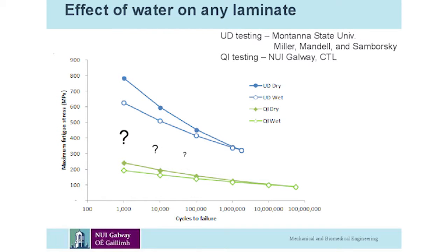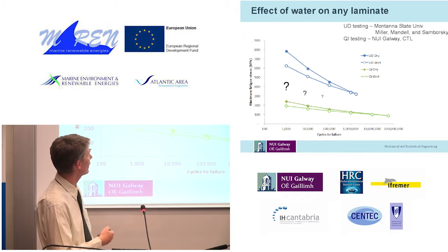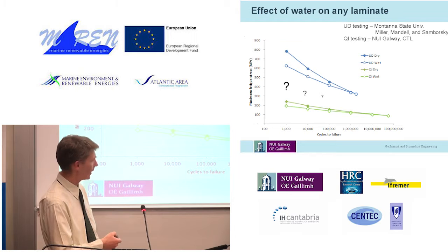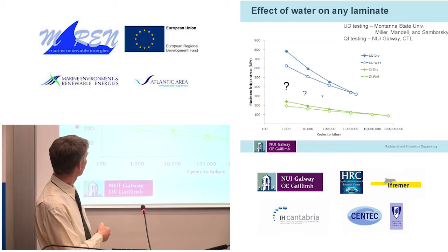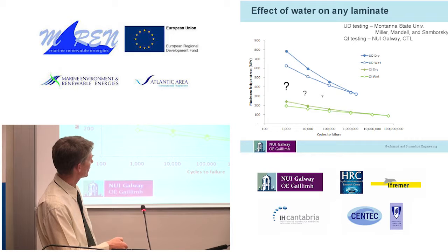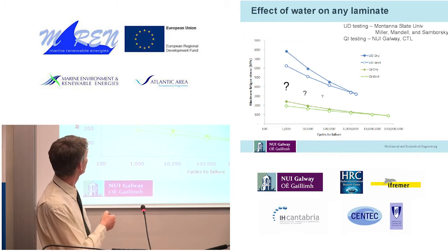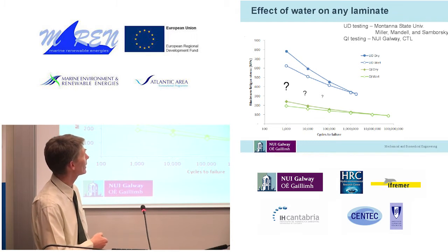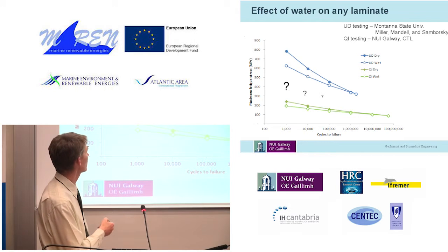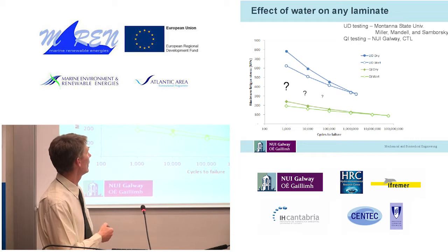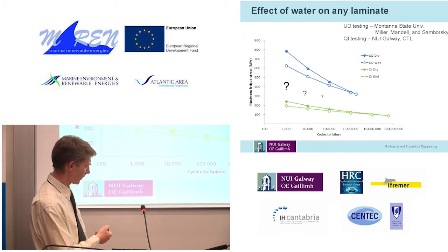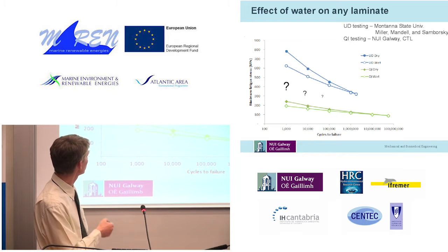So those are the quasi-isotropic results. And so to think about the effect that it has on other laminates, I've got on the graph here, I've shown the data on the quasi-isotropic material down here at the bottom of the graph, and up here I've found some data from some testing done by the team at Montana State University, and they've tested that unidirectional material in both wet and dry, and I've shown their results there. Just the question is, what about that laminate in between?